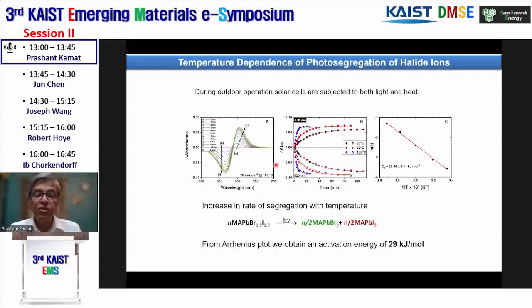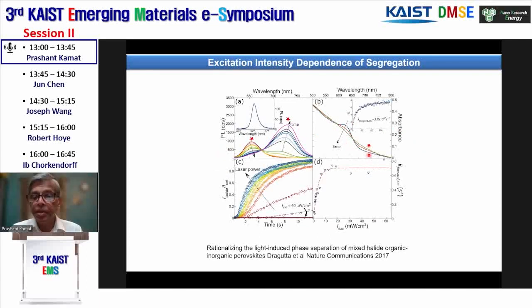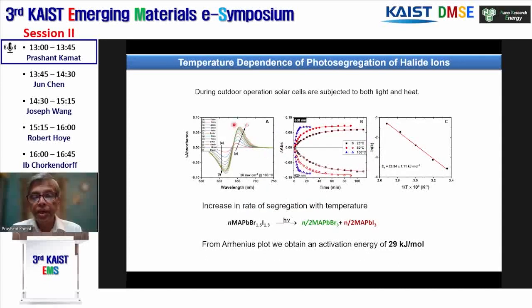So again, we followed the change in the absorbance. And again, you see here, this is the difference absorption spectrum from the previous slide, these two peaks here. This is decreasing and this is increasing. So this is shown in a more clear way in the difference absorption spectrum. So one is going down and another is coming up. So we can follow this absorbance and plot over time and get the kinetics of segregation under these conditions. Again, I have to caution you, this rate constant we measure is sensitive to the light intensity and the type of composition you have. Again, we can do the Arrhenius plot and get an activation energy of about 29 kilojoules per mole. And so this is for this one.